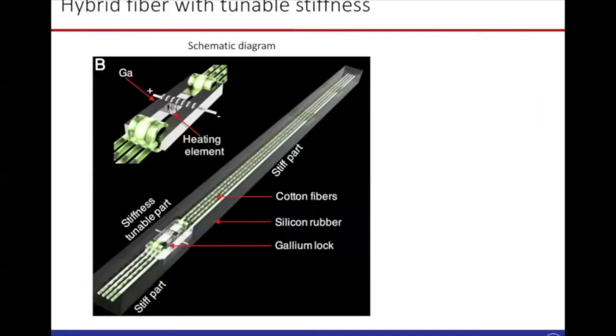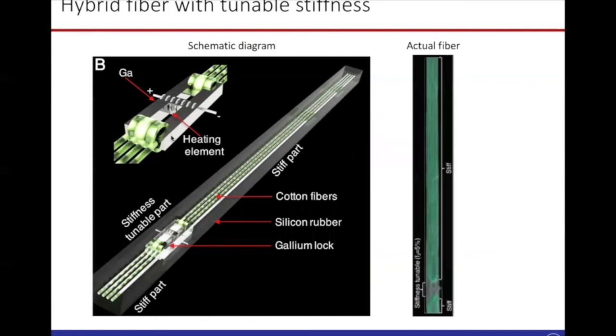Now, this is the schematic diagram of our hybrid fiber. The green part indicates the stiff part, and here is the soft part, and you can see a locking mechanism inside. Here is the enlarged view of the locking mechanism. You have a gallium structure with a heating element in the middle. The gallium connects the two stiff parts. When you supply current to this heating element, it generates heat, the gallium melts, and then it disconnects these two stiff parts. And when it solidifies, it will reconnect the stiff parts. In that way, you can either lock or unlock the soft part.